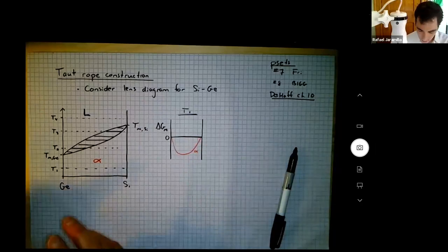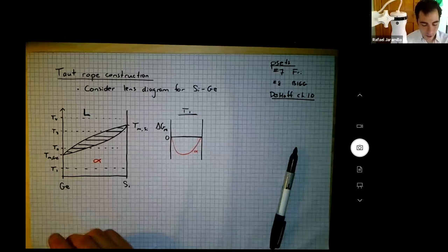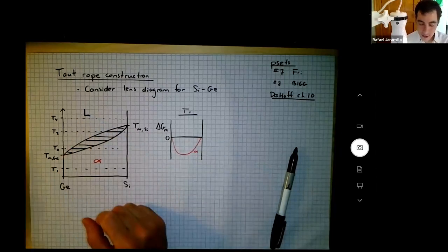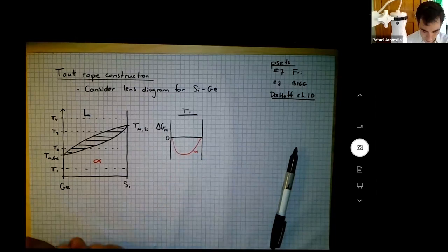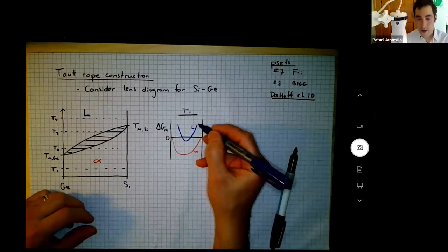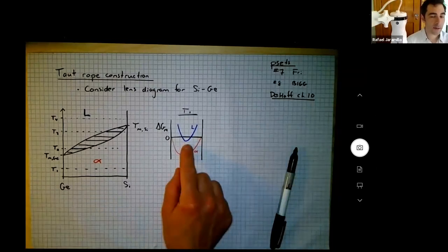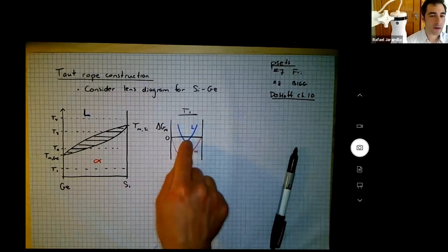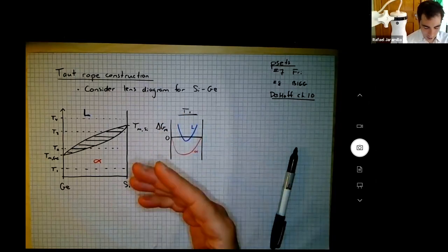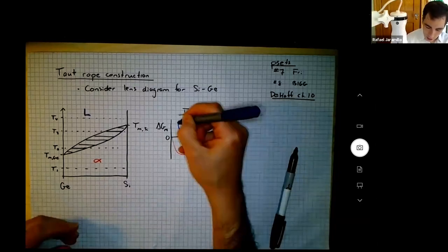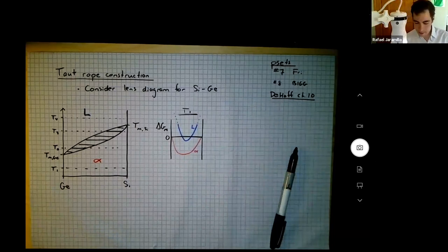All right. Now, the slightly harder question: what should my solution model for the liquid phase look like at T1? This is new. This you know, but this next question I asked, this is new. Okay, I'll tell you because it's new. It's going to look something like that. Why is that? This is a model for the free energy of a phase which is never stable. We can still model it though. You see, I'm not drawing it across the full composition range. This model shoots up to some high value at the two y-axes. Why? Because it takes free energy to turn germanium or silicon from alpha into liquid at this temperature. So we have to imagine this shooting up to some high value, but we can draw it and we can think about it. Okay, that's T1.